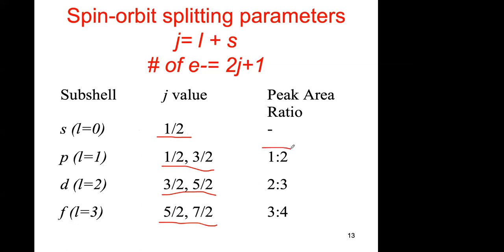And also the ratio of the peaks will let you know which orbital it is, if it's P, D, or F. If it's a P, you will have two peaks, and the ratio is 1 to 2. D will be 2 to 3, and F will be 3 to 4. That's really a fingerprint that you can use to identify the orbitals being analyzed in the spectra. And the number of electrons can be determined by 2J plus 1 for each of the levels.